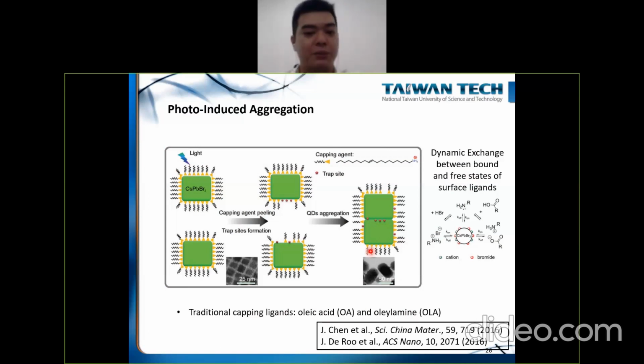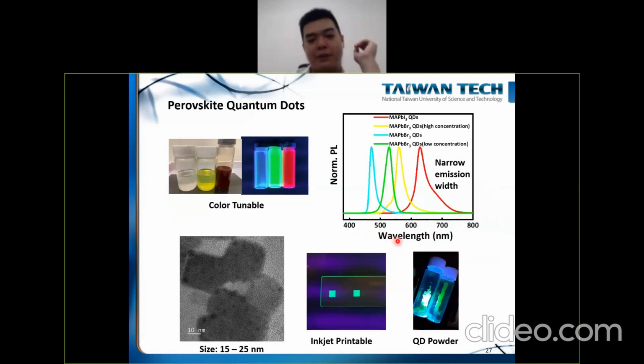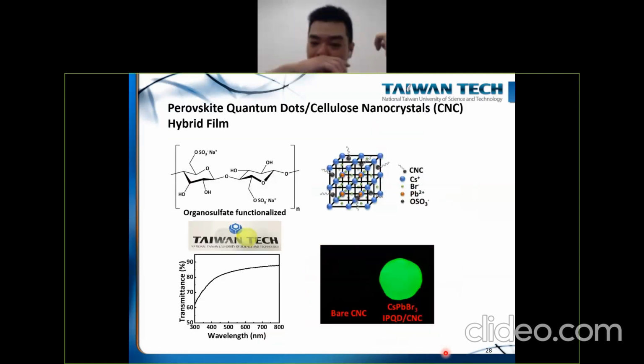So in our lab, we try to synthesize some perovskite quantum dot materials. For example, these are blue, green, and red emission quantum dots, and we characterize their size. And we collaborate with some groups on inkjet printing of nanomaterials. So this is inkjet printable, and we can also produce quantum dot powders. But the most recent project I want to share with you in the next few minutes is perovskite quantum dots with cellulose nanocrystal hybrid films.